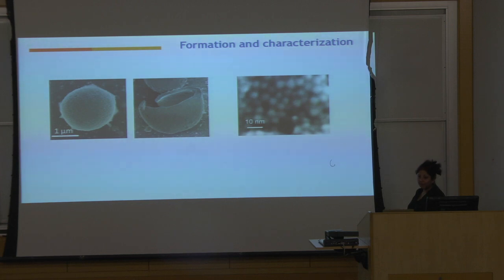We do SEM imaging. The first time you see this on images, you can't believe that you formed shells. Here's an entire shell. We managed to get some broken ones, and you can see that they're actually hollow. So this is the shell wall. It looks like a little hollow bowl. We did a close-up of the shell wall. These are with an SEM, not a TEM, so they look fuzzy, but we are really pushing the SEM to its limit. These are the nanoparticles in the wall.